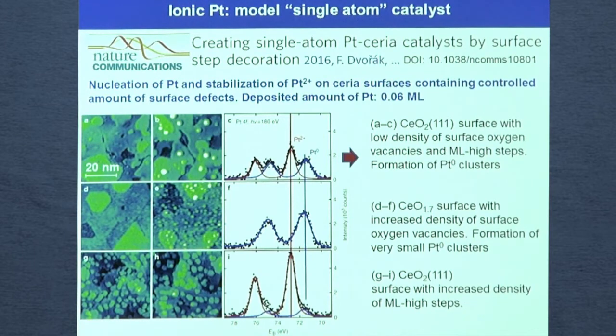Okay, previously I showed that we also have platinum 4+, but I forgot to say that platinum 4+ is not stable. It's some kind of defect where the platinum is in the lattice of ceria, and after annealing or reduction in hydrogen, the platinum 4+ is reduced. Well, so if it's flat, after depositing this amount we have platinum 2+ and 0. If we have the same surface but partially reduced, also with a very low concentration of steps, we are again forming platinum particles. This is also platinum particles.